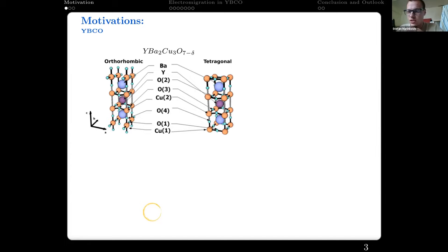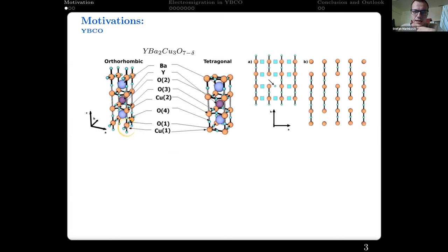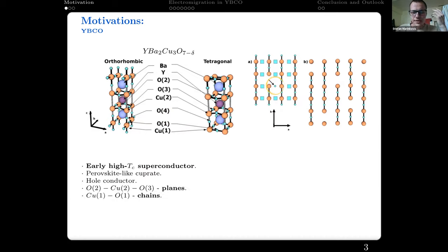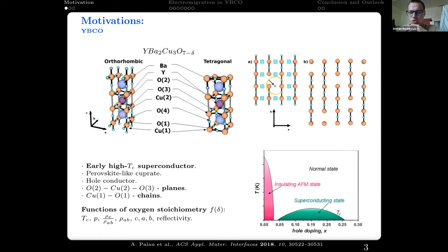I would like to highlight the structures of tetragonal and orthorhombic YBCO, where the orthorhombic material is the superconducting one at high oxygen content. In this orthorhombic structure, I would like to highlight the chains of copper and oxygen that exist in the AB plane, from copper one and oxygen one as marked here. They are important because they are the most probable reason for the significantly larger oxygen diffusivity of the oxygen in these chains, which allows us to use electromigration to tune the material, because electromigration is selective in materials where one atom has a much higher diffusivity than the others.